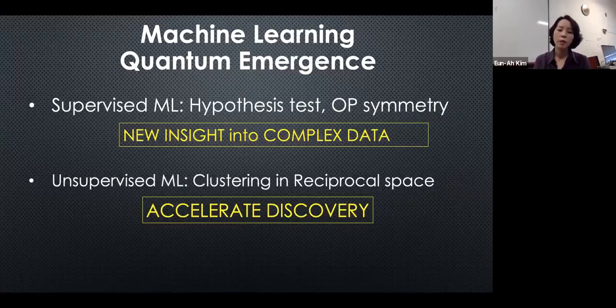And I also talked about unsupervised machine learning, where we were clustering X-ray diffraction data of large volume to make use of, instead of being weighed down by the volume, we were able to make use of the volume by employing the clustering algorithm, which really only works when you have statistics. And we were able to confirm the nature of upper transition and discover signals that were so far unknown as a way of looking for intra-unit cell changes in X-ray data at the lower transition.